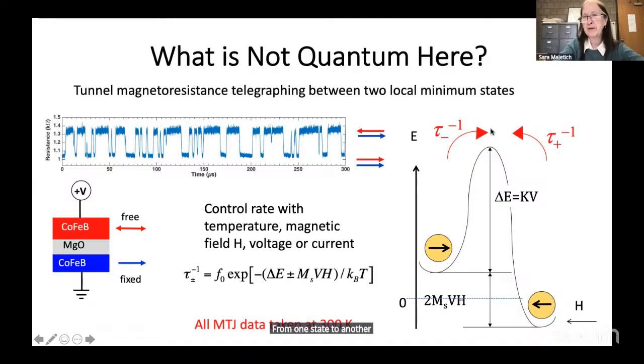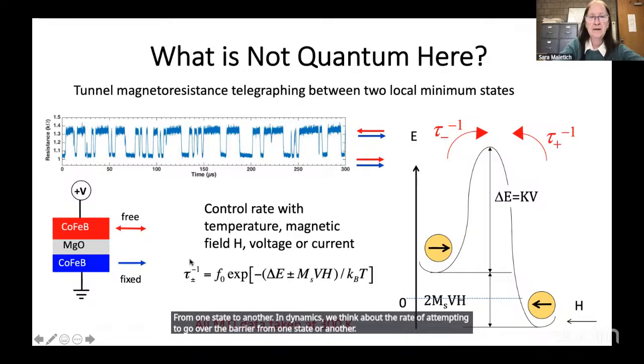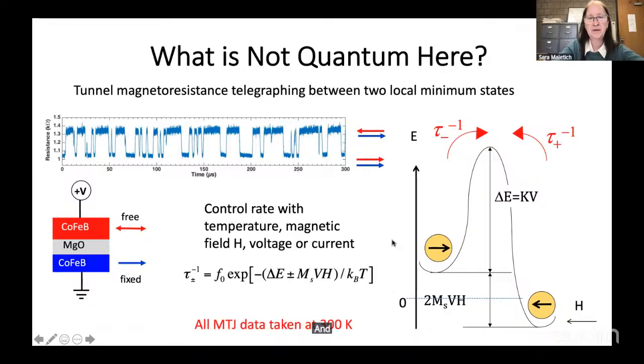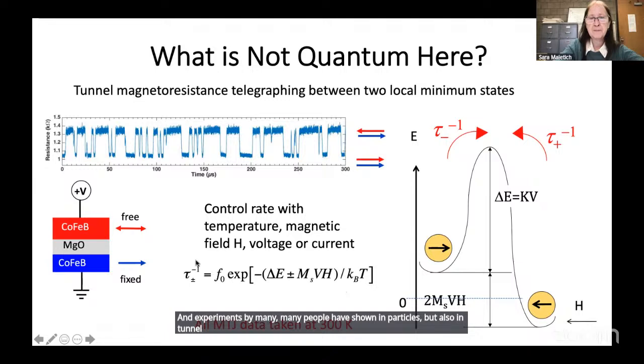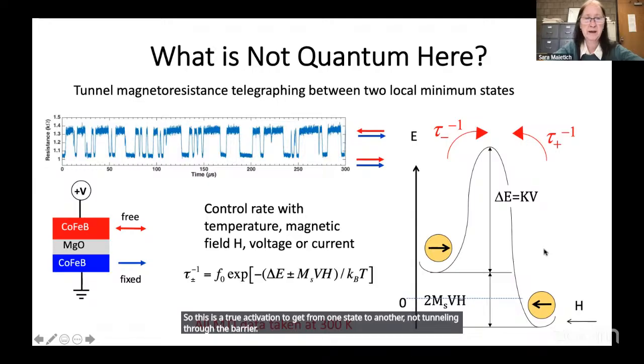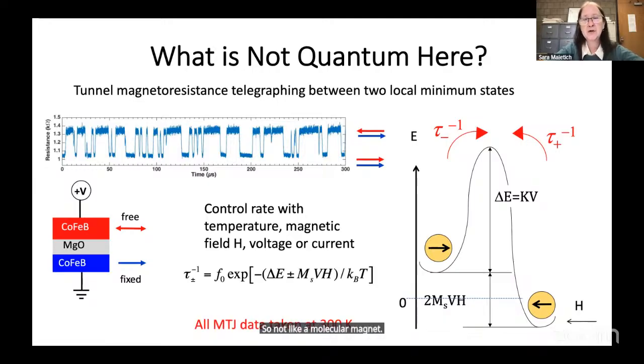In dynamics, we think about the rate of attempting to go over the barrier from one state to another. And experiments by many, many people have shown in particles, but also in tunnel junctions, that you get a rate that depends on this energy barrier. You can tune it with an external field or with the temperature. So this is a true activation to get from one state to another, not tunneling through the barrier. So not like a molecular magnet. All the data that I will show you is taken at 300 Kelvin.